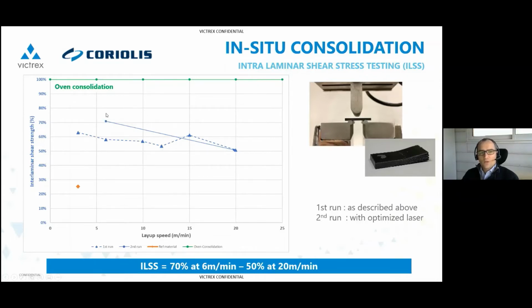As you can see here, we have a drop in terms of mechanical resistance. To be fair, we want it to be around 80%. We are slightly below at a low speed; we ended up at 70%. And then again, when you increase the speed, the quality of the laminate is getting worse, so you have a loss in mechanical strength. But we believe this can be optimized and pushed a little bit more toward the top, and still try to reach 80% mechanical strength compared to an oven consolidated coupon.